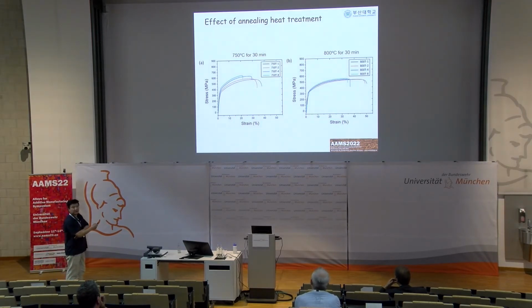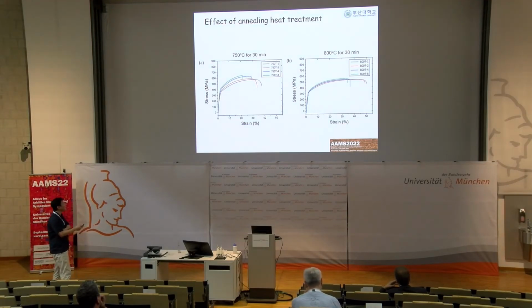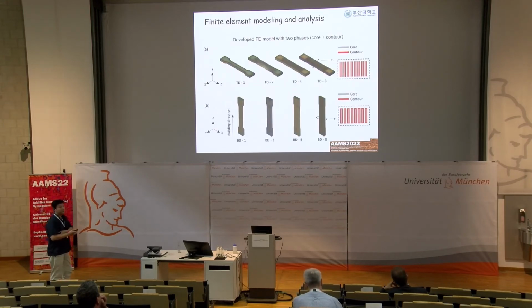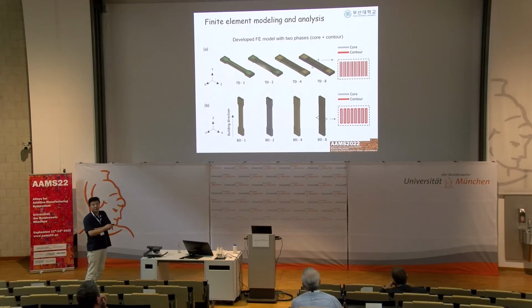In the case of the stress relieving heat treatment, we are reducing this effect, but we don't get rid of the size effect. In the case of the homogenization heat treatment, we can really get rid of this size effect. So that's why we suspect that this is strongly influenced by the solidification cell size in the contour scanned area. And finally, we have developed a very simple model based on the microstructural understanding of this.